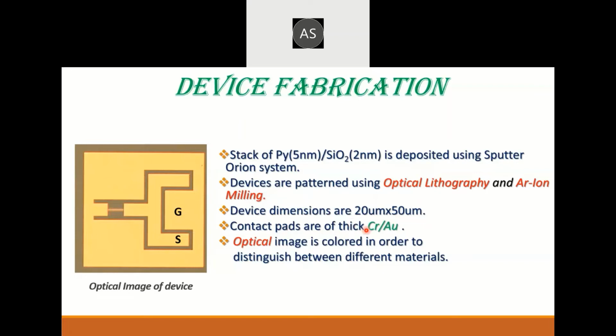So it's a simple fabrication for this. And the only thing is that we have actually used some thick chrome gold, close to 200, 250 nanometer, for this RF measurement.